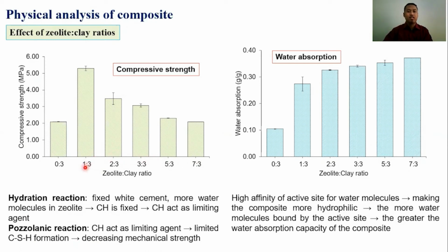We try to explain this phenomenon based on the hydration and pozzolanic reaction in the composite. In the hydration reaction, with the mass of white cement fixed and more water molecules bound in the zeolite's framework, it could produce a fixed amount of calcium hydroxide or Portlandite mineral, or CH. This product here acts as the limiting agent. Then, in the pozzolanic reaction, when calcium hydroxide is the limiting agent, the calcium silicate hydrate produced is also limited. It caused a decrease in mechanical strength.